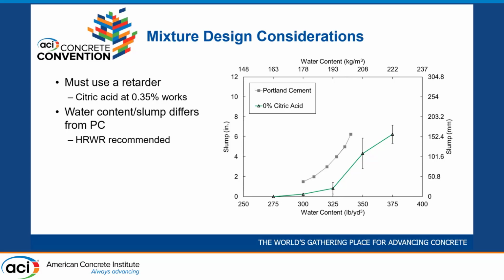And so you can see if you don't use any citric acid at low water contents down here, it's very difficult to achieve any slump at all. Again, I don't recommend ever not using citric acid, but additional citric acid improves the workability for the same water content. So this is the 0.35% citric acid dosage we usually use.